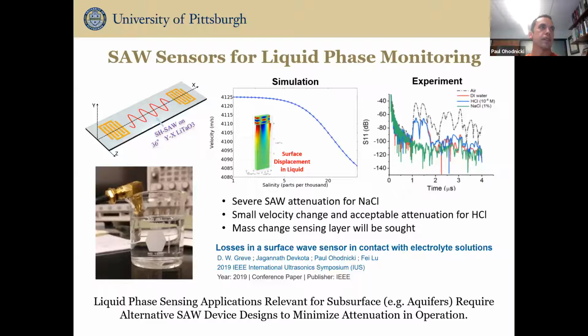There's also the opportunity to use these devices for liquid phase monitoring. The challenge with liquid phase monitoring, though, is that because this is an acoustic device, unless you modify the standard operation of the device, you'll lose a lot of energy to the solution phase because of the interaction of the acoustic wave on the surface with the surrounding medium.